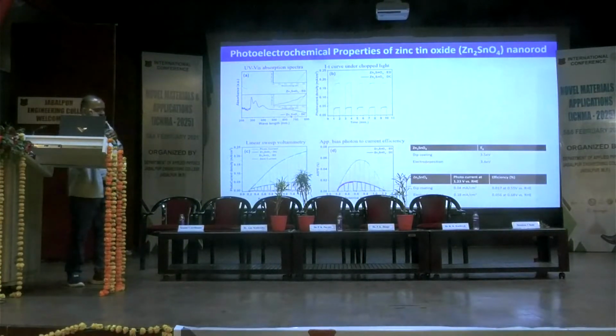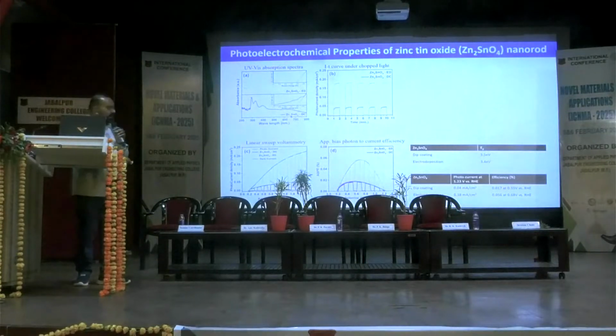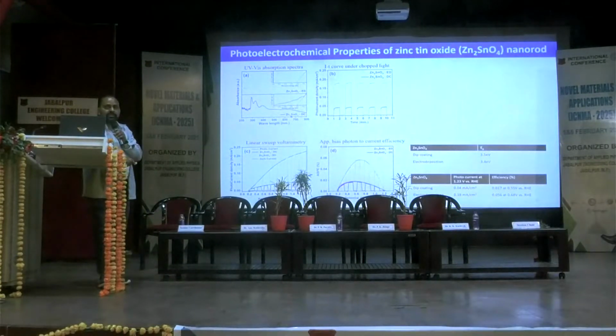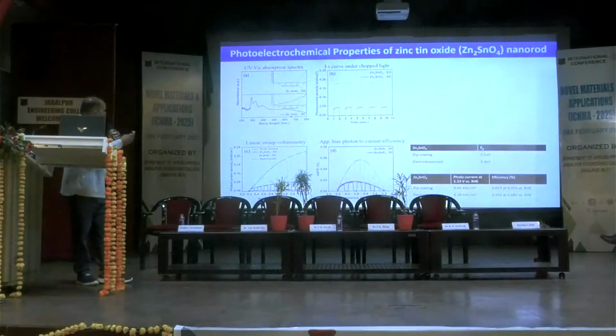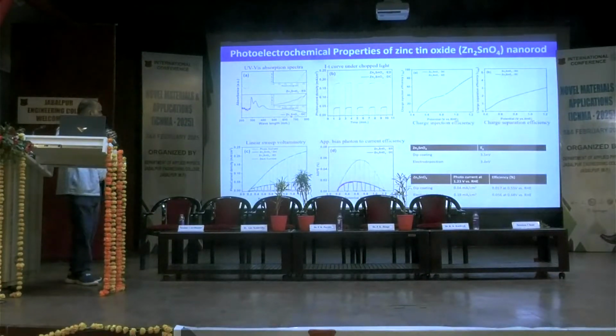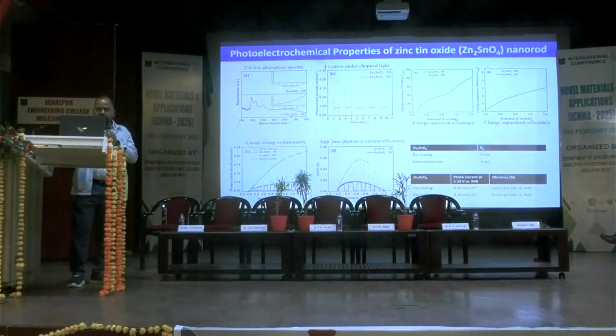So the logic we have given is that in the electrodeposition system, the seed is more compact and has a cleaner nature, so the structures are also denser on that system, and the layer is very thin at the bottom, basically the bottom of these rods. So we are getting more active surface at the electrode. We also calculated the electrochemical surface area, and that was very high. Then we investigated the charge injection capacity and separation performance. In all these calculations, we found that the electrodeposited seed layer showed much better performance.